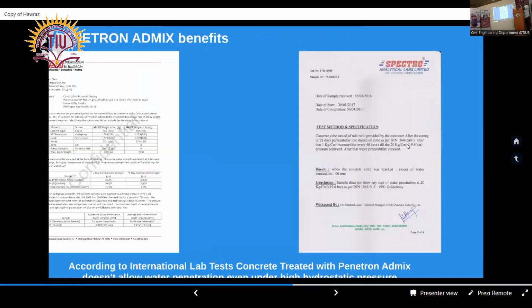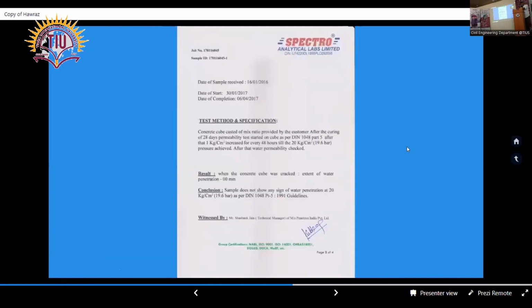Here's another test which was carried out in India. It states that after curing of 28 days, a permeability test on the cube as per DIN 1048. The result says that the extent of water penetration is 0.